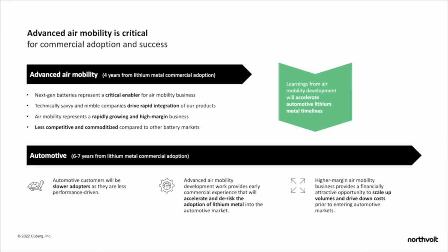to air mobility. Automotive customers are really slower adopters, and not intrinsically because the companies are slow, although maybe some of them are as well, but because the value proposition for energy density is not nearly as high. I would argue it's actually 1 to 2 orders of magnitude lower in terms of the value proposition they derive from energy density compared to what air mobility derives from energy density.